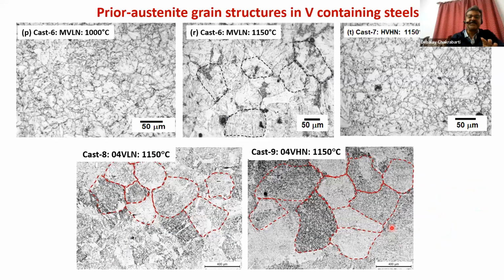Vanadium steel is much better in this respect. You can see it can have coarse grain size, but uniform grain size. This is the austenite grain size that's happening at high temperature. Depending on reheating temperature, grain size can vary. But the good thing is, grain size variation does not appear. Here, the grains are uniform in size.